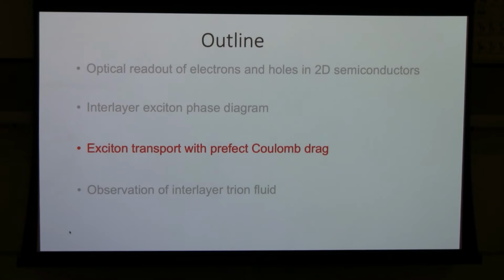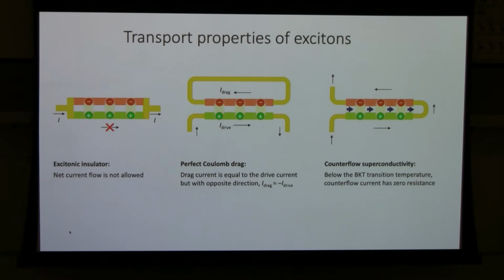Next I would like to talk about how we can probe the dynamic behavior, how excitons transport, and look at correlated electron and hole transport. When you have electron and hole bilayers, one way to look at them is direct electrical transport measurement. For example, if you have contact to both layers at the same time, you'll find it's not possible to pass a current through, because if it's only bound excitons, it's a neutral particle and cannot carry net charge. On the other hand, if you can make separate contacts to the electron and hole layers, you can pass a drive current in the hole layer,